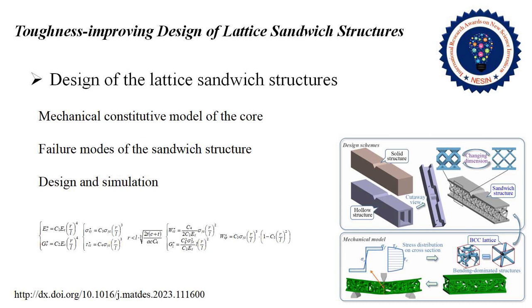Then, we describe our deduction by simulation and experiment. For simulation, we solved the flow stress in combination with the Johnson-Cook models. The results show that, when using the simulation method, we can predict the impact toughness of the samples. The change trend of the impact toughness is consistent with the actual test results. Therefore, the method of simulation analysis can be selected to drive the design of BCC lattice sandwich structures, and it can also predict or analyze the impact toughness of components.